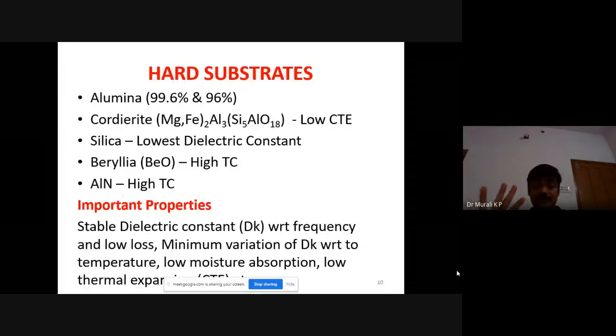So it is always better to select a material which doesn't have much variation of dielectric constant with respect to temperature, and low moisture absorption. These materials should not absorb moisture, because when moisture is absorbed, as you know, the dielectric constant is very high, and more than that, the loss is very, very high for water. So that will increase the total dielectric loss.